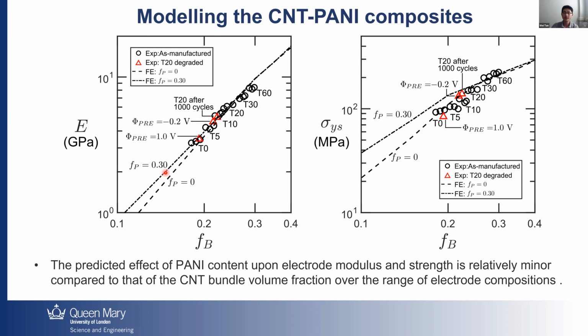That proves actually for the mechanical part, it's really the backbone that is taking control and dominating the mechanical behaviors. The reason why we see some change in the mechanical properties is because there's a shrinkage and swelling of the CNT during this PANI coating. So essentially, it will also affect the mechanical properties.